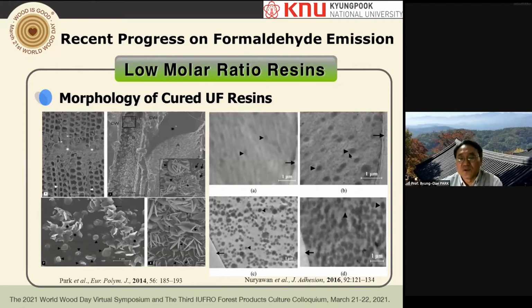And also we did look at TEM. This is high molar 1.6, this is 1.0. The 1.0 low molar has many more dark spherical particles. I believe these are responsible for the crystallinity of these low molar ratio resins.